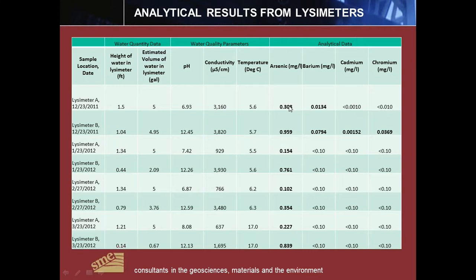Initially, it appears that the arsenic levels were higher in the recycled aggregate blend as opposed to the limestone, and that over time the limestone cleaned up faster, and we believe that this is primarily due to the amount of water that was collected. We had more water flowing through the limestone base than through the blended foundry sand concrete base.